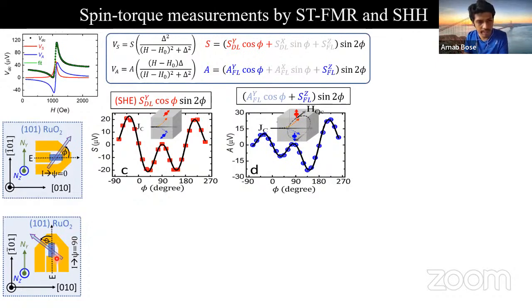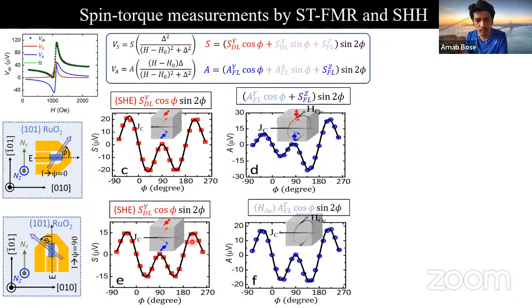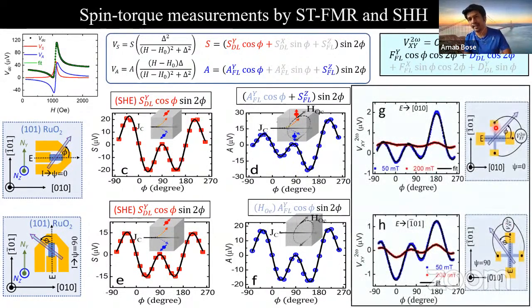But whenever we do the experiment by running current in this crystallographic direction, we see the regular response of this symmetric and antisymmetric Lorentzian. Both can be fit using the standard spin Hall effect and standard Oersted field. So we have strong crystallographic direction dependence of these extraordinary torques. So we want to cross-check this, or verify this, by doing another experimental method, which is the intense second harmonic Hall measurement.